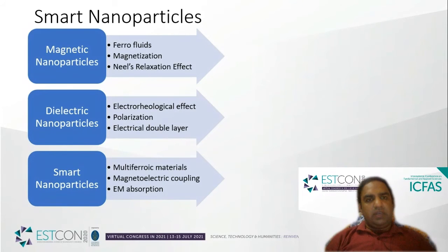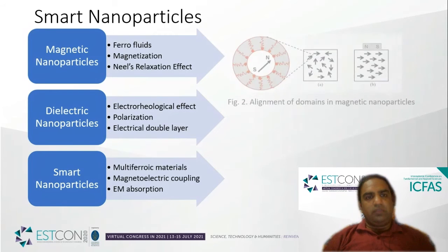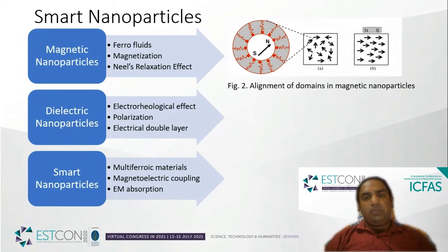But what are smart nanoparticles? First, we have the concept of magnetic nanoparticles, which are the ferrofluids, in which we produce magnetization by applying an external magnetic field, which actually aligns these domains of the nanoparticles in the direction of the magnetic field. So if we change the direction of the magnetic field, the direction of the domains can be changed. So it also produces the Néel relaxation effect, which is also the same: as we change the direction of the magnetic field, it changes